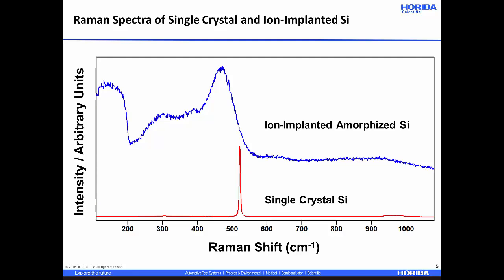In the semiconductor industry, ion implantation is used to introduce dopants — boron, phosphorus, or arsenic — to the semiconductor silicon. That is a process of ion bombardment. If the flux, energy, and masses are sufficient to disrupt and break up the crystal lattice, one loses the long-range translational symmetry. Here we see a Raman spectrum of silicon implanted with arsenic at a very high dose; the crystal lattice has been entirely broken up, and we get a Raman spectrum that looks essentially like that of amorphous silicon.